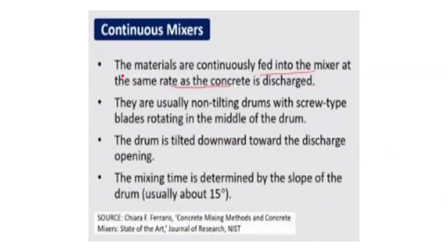So now let us go to the continuous mixers type, okay. In this case, the materials are continuously fed into the mixer at the same rate, okay, as the concrete is discharged. They are usually non-tilting drums with screw-type blades rotating in the middle of the drum. The drum is tilted downward toward the discharge opening. The mixing time is determined by the slope of the drum, which is again taken about 15 degrees.